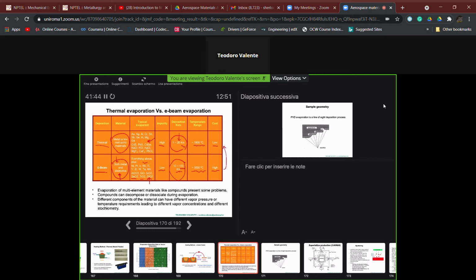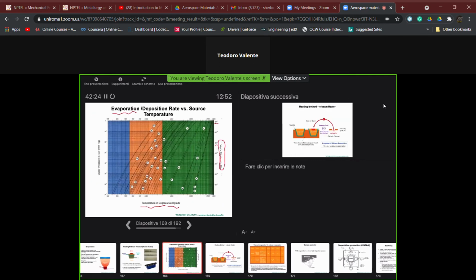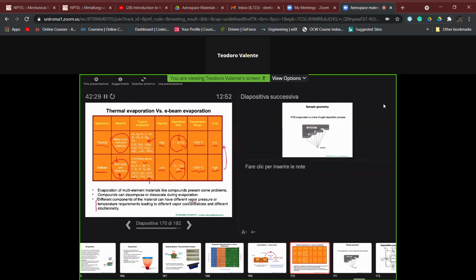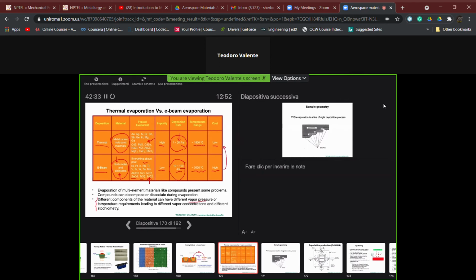We can make something to improve these, as we will see later. But again, with our improvement, we can achieve coatings in a reasonable industrial time, which have a final thickness of some micrometers. There is also another important issue which must be considered. If we want to deposit a sort of alloy, we have different elements in our materials, and different elements, as we have also seen here, can have different values of vapor pressures for the same temperatures. And so we could have a vapor concentration of the evaporated elements which is different from the source concentration. So we can have stoichiometry problems.